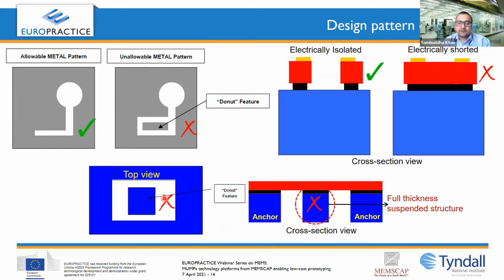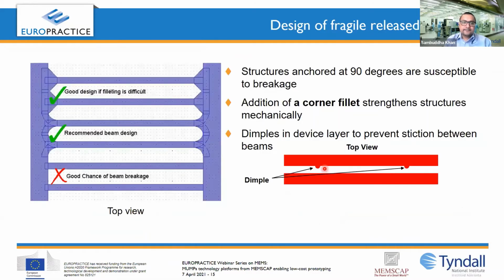trench, you cannot have a donut feature here. If you have a donut feature, they will actually create a full thickness suspended structure. And in SOI MUMPs, this full thickness suspended structure is not allowed. During fabrication or after fabrication they might break and come down. So SOI MUMPs do not recommend people use full thickness suspended structures. That is not allowed at all.